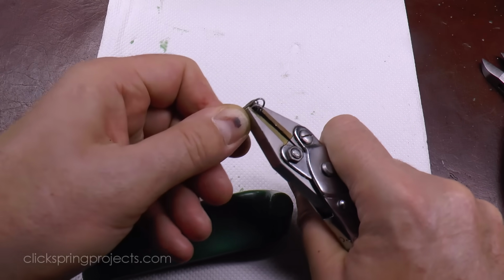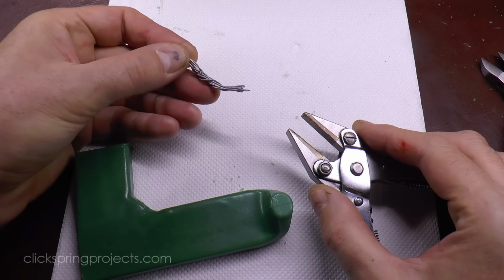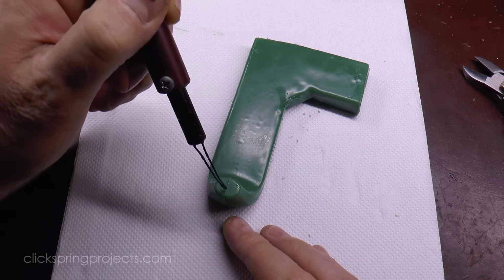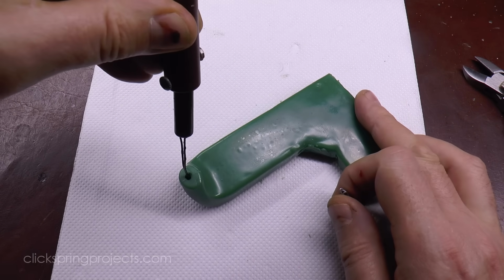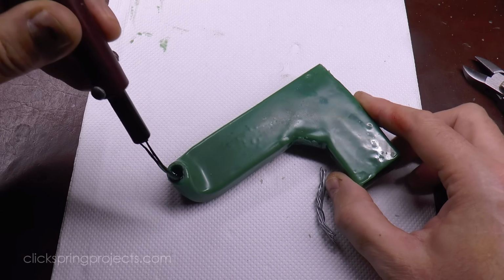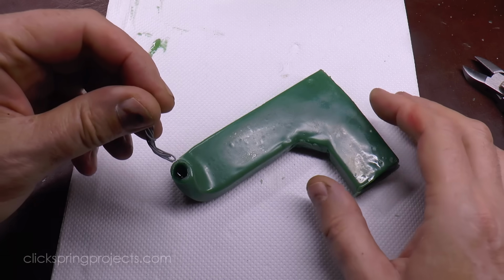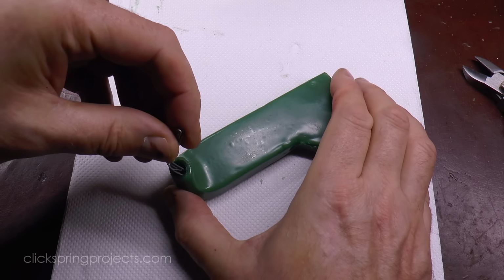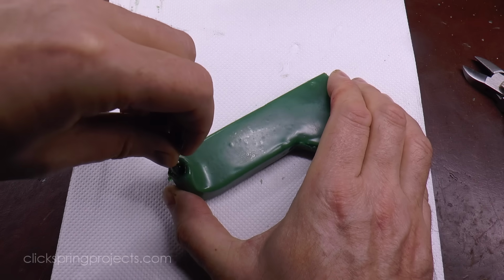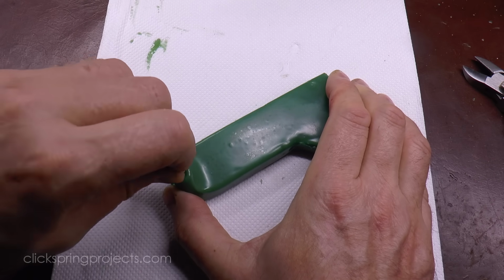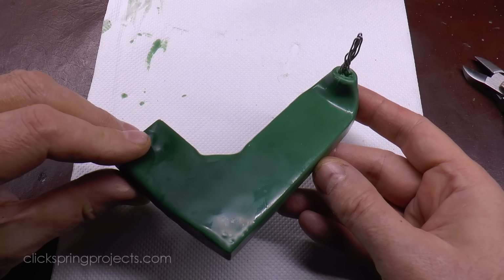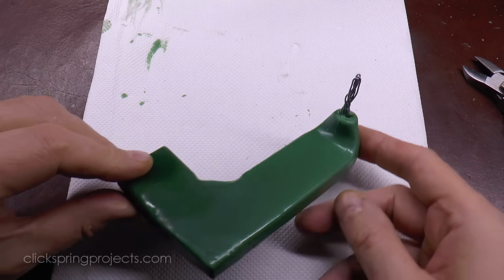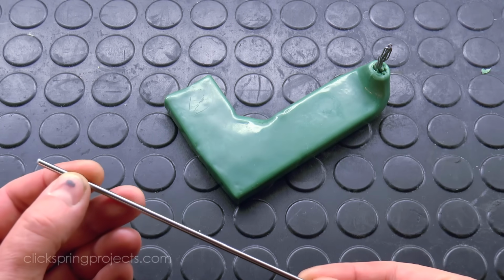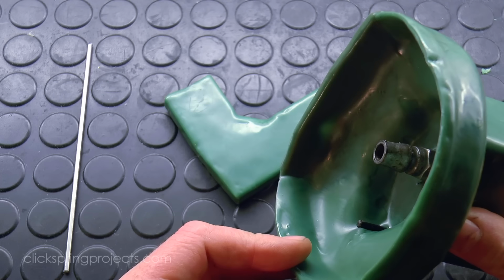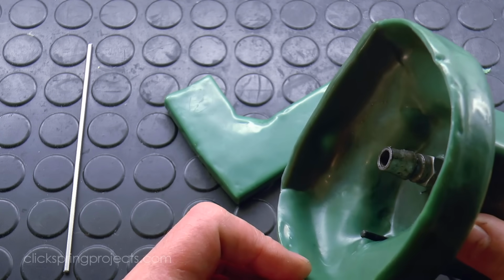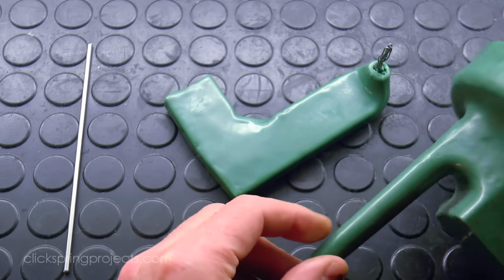It so happens that strengthening the pattern like this is a critical aspect of preparing it to withstand the physical handling involved when applying the ceramic investment. The pattern must be quite rigid, with minimal tendency to flex, to prevent unwanted cracking of the layers of ceramic after they've been applied. A long thin section like the sprue, for example, can be made quite rigid with a slender length of steel rod. The caveat is that each of the reinforcing elements must be placed in such a way as to permit their removal during the de-waxing stage.